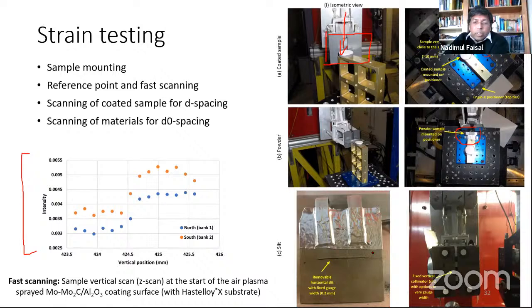Now, if you're playing with the gauge volume for the coating, you may put in some slit. And this is a very useful slit for testing some of these coatings. This is just an aluminum plate which has a very thin, 0.2 mm wide slit in it.